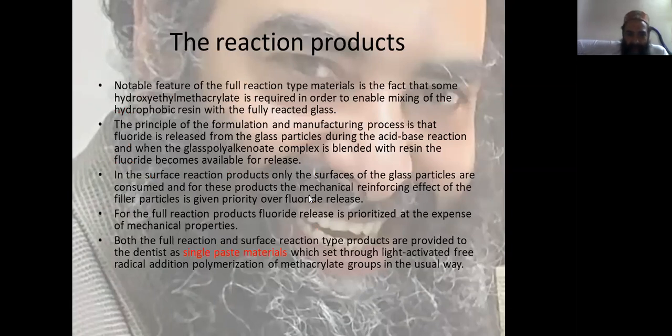Now, a prominent feature of the full reaction type is that some hydroxyethyl methacrylate, HEMA, is required to enable mixing of the hydrophobic resin with the fully reacted glass.